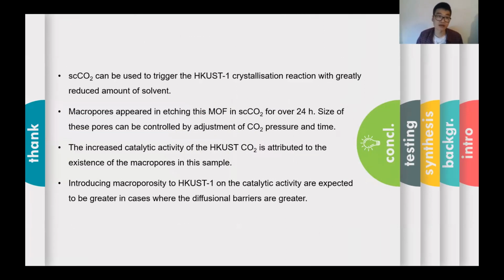To conclude, supercritical CO2 can be used to trigger the HKUST-1 crystallisation reaction with a greatly reduced amount of solvents. And we see that using CO2, macropores can be introduced in the MOF, and the size of the pores can be controlled by adjusting CO2 pressure and time. The increased catalytic activity in the MOF is really caused by the existence of the macropores in the sample, and the benefits of introducing macroporosities in MOFs are expected to be greater in cases where more bulky molecules are involved.